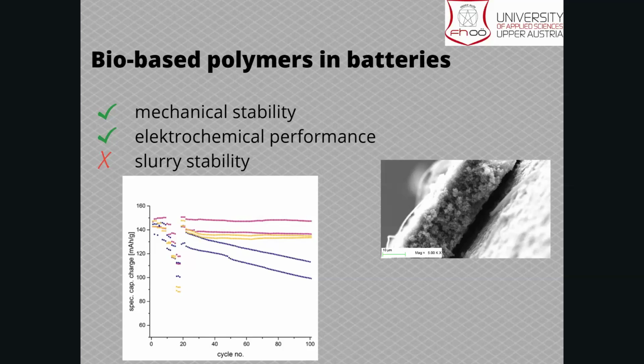And the two other ones, the yellow and the purple one, are blends with styrene butadiene and CMC, carboxymethyl cellulose, which was honestly not our initial idea, but it seemed to work out very well. And by now we have nearly 3,000 cycles and they're showing very, very high stability.